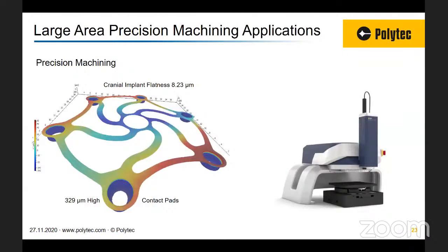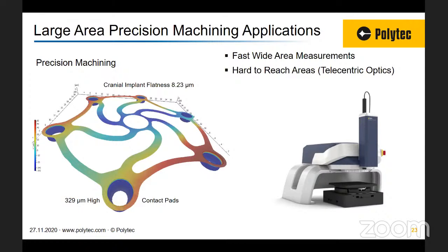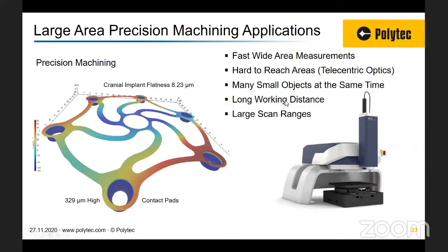So for the large area type applications, we like measuring flatness. Of course, we're measuring wide areas very quickly. We can measure hard to reach areas. So the telecentric optics has very good penetration into a surface. And we can measure multiple objects at the same time. We have long working distances, long scan ranges, and of course, we have a multi-sensor version of this instrument where we can put a confocal optical probe, so this can increase your spatial frequency bandwidth.